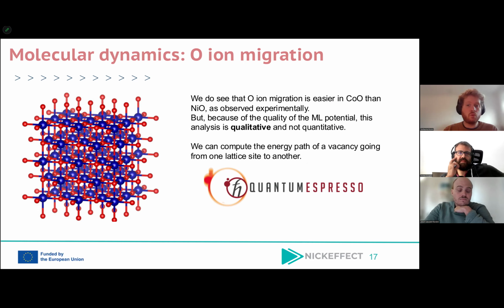And so we wanted to have something quantitative, and what we did is we computed the energy path of a vacancy going from one lattice site to the other, and we did that using density functional theory, that was with Quantum Espresso.